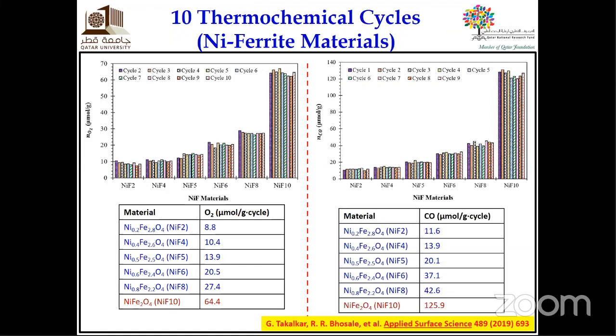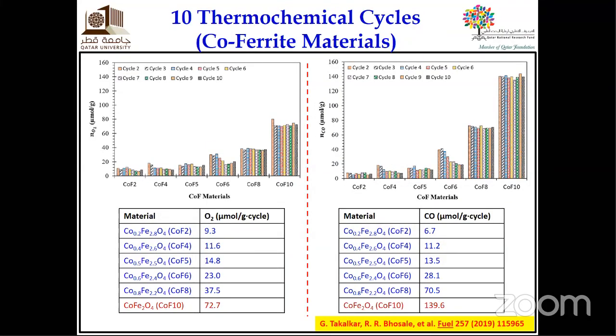This slide tells you about the nickel ferrite materials. I gave you all the information here: average amount of O2 produced per cycle per gram, and average amount of CO produced per cycle per gram. The nickel ferrite at the end is the highest. That's why I put that in red, and others are in blue because they are not as high as NiFe2O4, in terms of O2 release and CO produced. So it indicates that out of the 6 nickel ferrites we have synthesized, NiFe2O4 is capable of producing the highest. A similar thing was observed in the case of cobalt ferrite, that CoFe2O4 is capable of producing the highest.